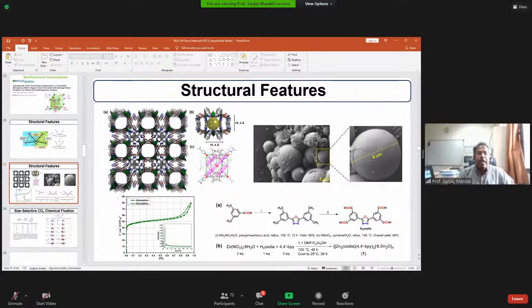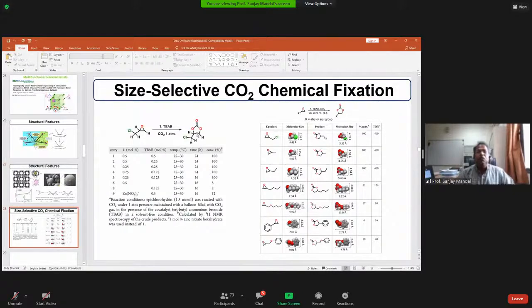And here again, we have a pore size close to 0.73 nanometers that is decided from gas adsorption and crystallography. So here again, what is very important is that this has become very size selective. We have shown that as you increase the size, your yield goes down, right? Your conversion of 100, 100, 100 goes to 31 as soon as you go to the propyl group. So this is showing that the CO2 activation is happening within the pore, because we look at not only the starting material but also the product side, because the product has to come out. And this size selectivity is very rare at room temperature and balloon pressure.